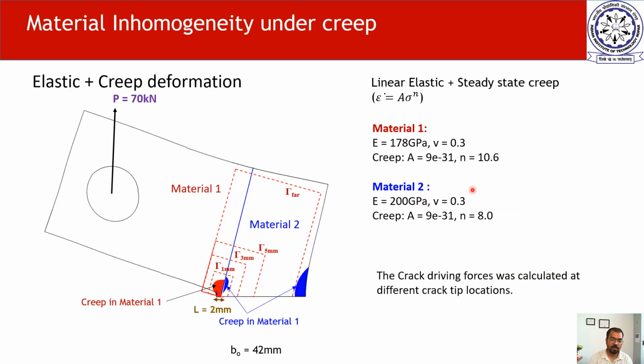So we did that for a specimen where a material transition happens from material 1 to material 2, and material 1 is in all other ways representing Waspaloy, a nickel superalloy with the creep properties and elastic modulus, and material 2 is a hypothetical material with elastic modulus of steel, but the Norton's law coefficient we have kept constant in these two, and we have just taken the creep exponent to a smaller value.